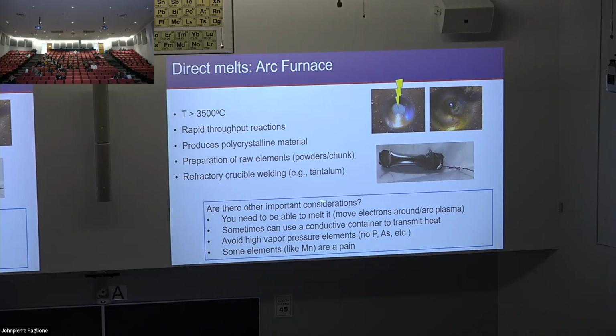In addition to that, we use it for preparation of refractory crucibles. So this is a tantalum tube, which generally speaking is difficult to work with to make a sealed vessel. But with an arc furnace, we can do that. We can carry out reactions inside of here. So, we heard about alumina crucibles, but in fact, there's many other types of crucibles that we need to think about if we're dealing with elements that are very reactive. So tantalum is one powerful way to do this.